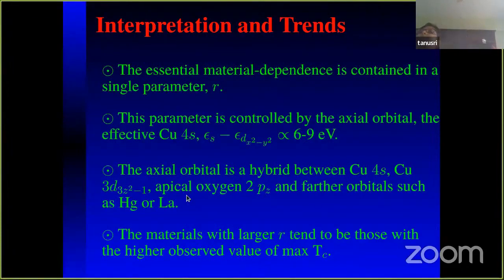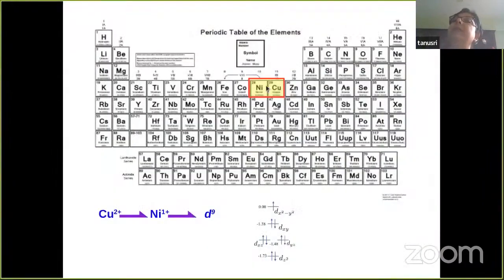So for the cuprates, our understanding was the following: the essential material dependence is contained in a single parameter R, and that is controlled by this axial orbital, which is a hybrid between the copper s, copper 3z squared, apical oxygen pz, and further orbitals. And we concluded also that materials with larger R tend to be those with the higher observed value of Tc at optimal doping.